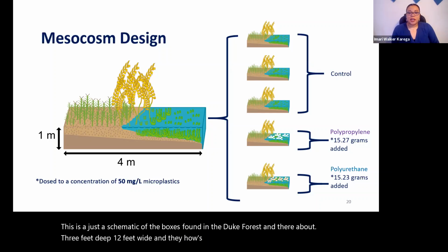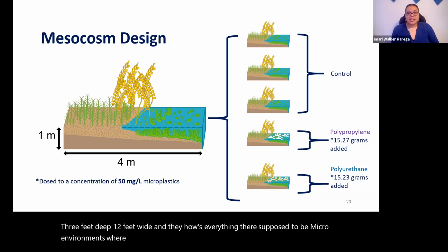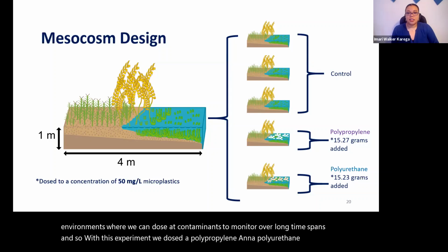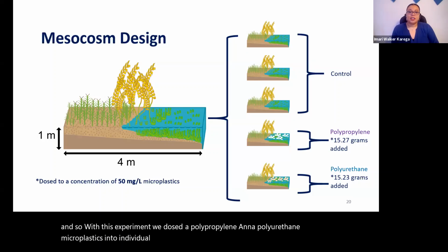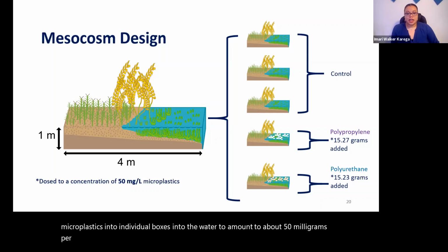They're supposed to be microenvironments where we can dose contaminants to monitor over long time spans. So with this experiment, we dosed polypropylene and polyurethane microplastics into individual boxes into the water, to amount to about 50 milligrams per liter of microplastics in water.